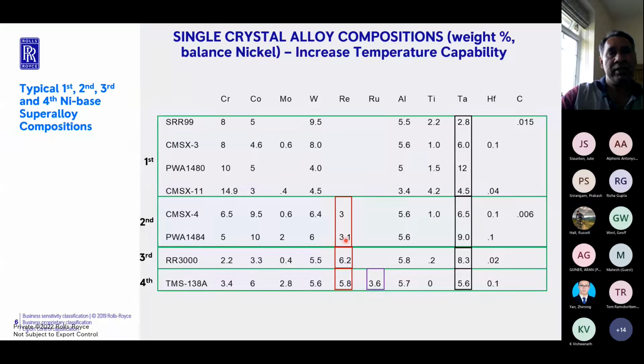Now, the important thing to note is that rhenium is not an element that occurs in abundance in the Earth's crust. Actually, it's a byproduct of copper. So I don't know it off the top of my head, but for several tons of copper, you might just get a few grams or a few kilograms of rhenium. So rhenium is a pretty expensive metal because the amount you can claim for a given amount of copper is quite small. So whilst it's an important element that's added in second generation alloys for strength, it comes at a cost to sustainability. So second generation alloys are markedly more expensive than first generation alloys.